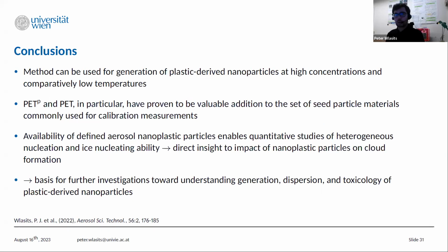So I want to conclude. This method can be used to generate plastic-derived nanoparticles, even plastic-derived sub-10 nanometer nanoparticles, at high concentrations and comparatively low temperatures. If you compare to silver with around 1000 degrees Celsius, it's pretty low temperatures.